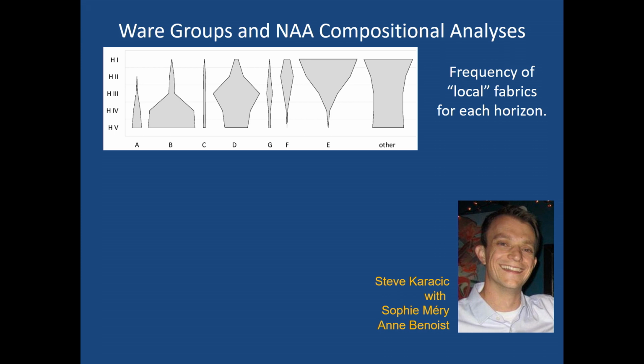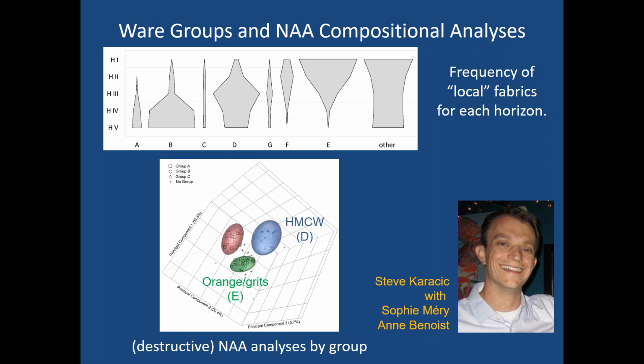But we can take that a step further if we can apply a more high-powered technique like neutron activation analysis in this sense, which allows us to do the trace element compositions of these different ware groups and to really pull them apart. And so we can see fabric D, for example, handmade courseware, is distinguishable from fabric E, the orange gritware, when we do these kind of detailed analyses.